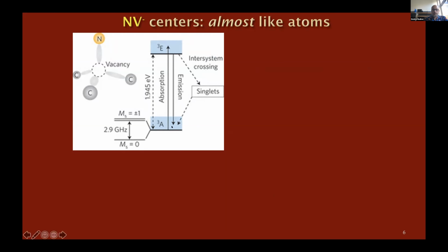So this is the ground electronic state here, and this is the vibronic excitation band, and the same thing is happening in the excited state. So when we are looking at absorption, we usually have electronic excitation accompanied by some vibrational excitation. Then we have non-radiative decay on a picosecond time scale over here to the bottom of the band. And then there is normal emission after about 10 or so nanoseconds back to the ground state. And again, we can excite vibrations when we do this. And so you can see that this leads to the shift.